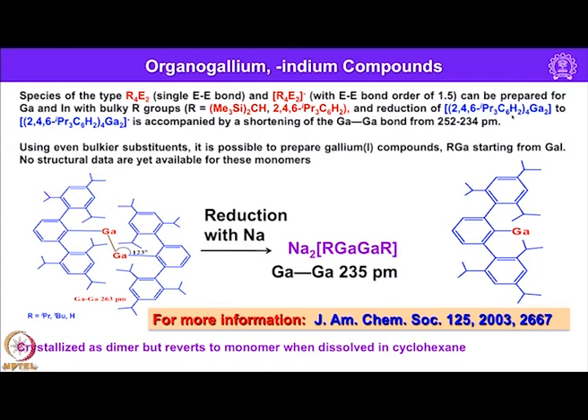reduction of this one, essentially this gallium compound, is accompanied by a shortening of the gallium bond from 252 to 234 picometer. That means a normal gallium single bond distance is 252, and if it changes to 234, it indicates the multiple bond character in this one. So, using even bulkier substituents, it is even possible to prepare gallium 1 compound having one coordination like RGa starting from gallium iodide. No structural data are yet available for this monomer I have shown here.